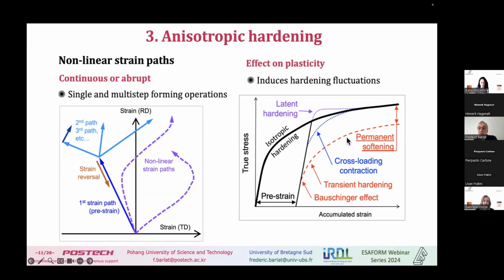And one thing I forgot to mention about the Bauschinger effect: not only do we reload at a lower stress, but usually we get some kind of permanent softening, so that the new curve never recovers the level of the isotropic hardening curve. So we can get all those effects. And to represent that, because we cannot do all possible cases of strain path change, we have to rely on a few changes only and assume the model is accurate enough to represent all that.